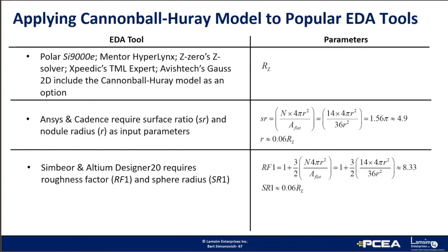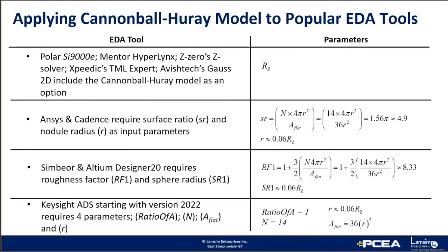Simbeor and Altium Designer20 require only 2 parameters. Roughness factor, RF1, and sphere radius, SR1. Similarly, RF1 can be simplified to a constant 8.33, and SR1, again, 0.06 Rz. And finally, as of release 2022, Keysight ADS has adopted the Cannonball-Huray model and needs these 4 parameters. You can still use my cannonball stack method by using 14 for N, ratio of A equals 1, and then 0.06 Rz for R and 36 R squared for A flat. So in all these cases, if you know Rz, you can use these tools.